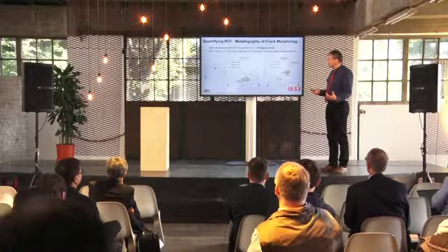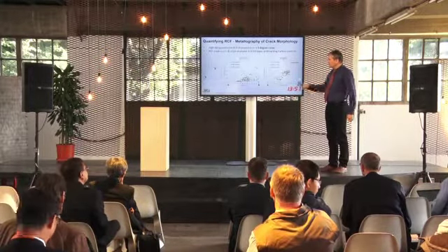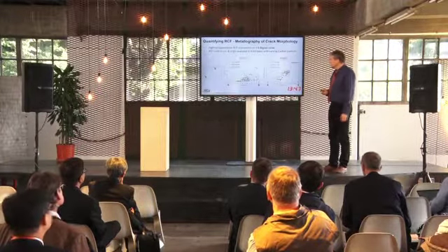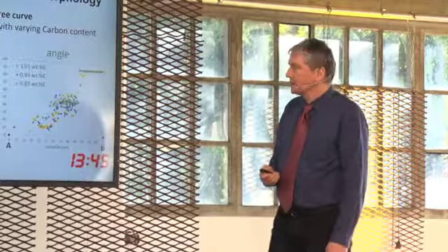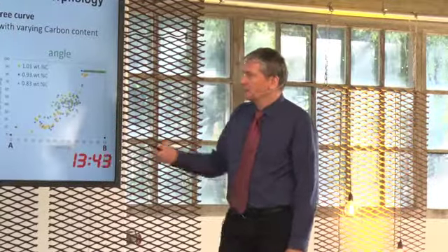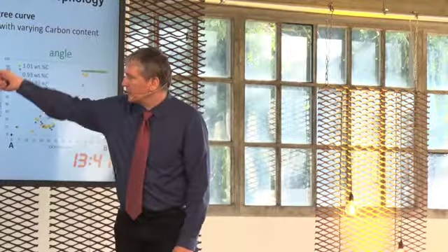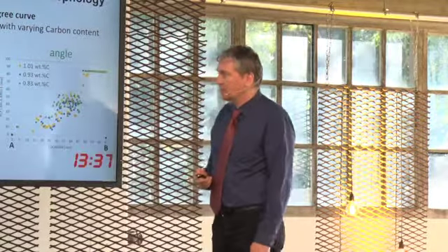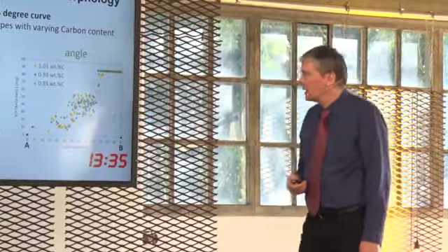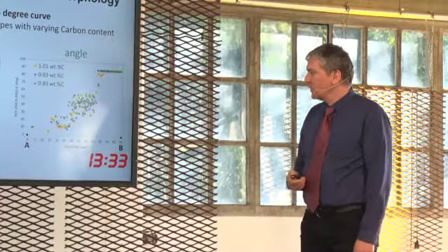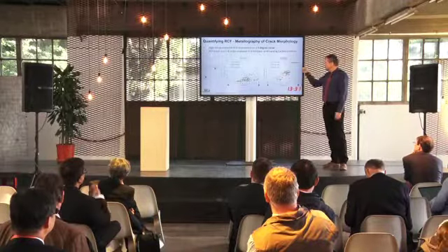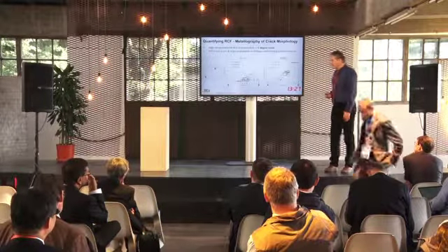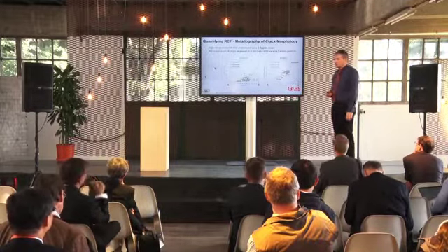When you line up the results from the gauge face, from point A all the way to point B, you start seeing some trends forming. For the depth, the 1% carbon has a higher crack depth than rail that has 0.83% carbon. But for the angle, all the angles for RCF cracks lined up pretty nicely for all those rails. So that sparked the idea to do some of that research in RCF.